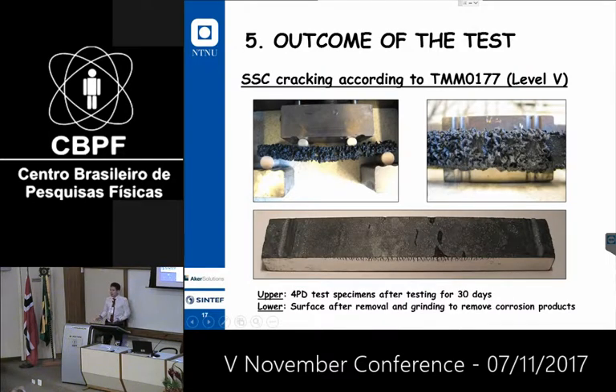So what happened during the test? The material failed. It failed level 5, and this is contradictory to some literature and to the material specification in the data sheet. It failed quite dramatically, not only severe corrosion, but also pitting and cracking, almost half of the thickness of the sample.